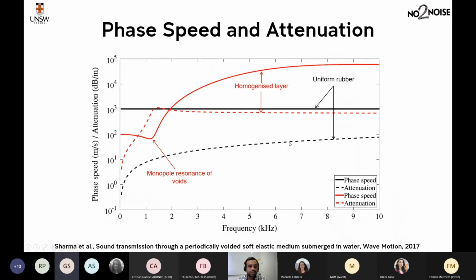So this slide shows the phase speed and attenuation in the media. Here I am comparing the phase speed and attenuation in the homogeneous rubber medium, or uniform rubber medium, with the homogenized layer, which is created by homogenization of your cavities in the rubber medium. So as you can see, they behave very differently, right? Here, for uniform rubber, as you know, the sound speed in general does not change with frequency,